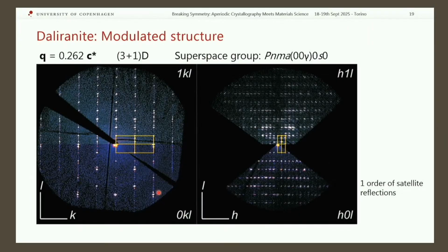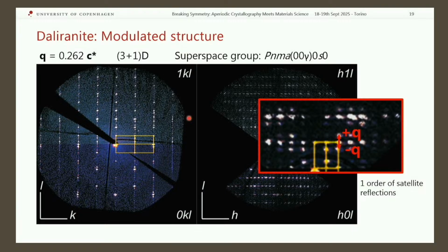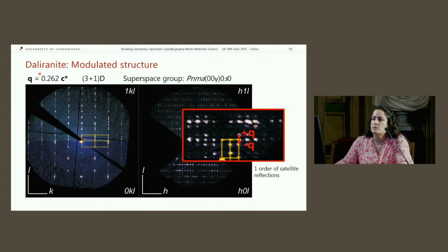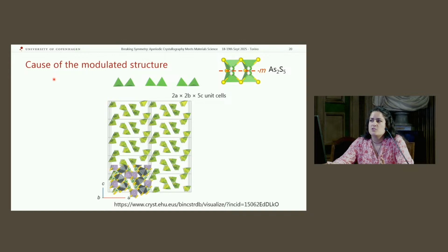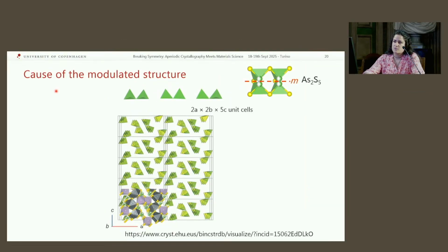But if we look at the reciprocal space, we see that our yellow unit cell here is not explaining all the peaks. So we have satellite peaks that are indicating there is some modulation going on, and we need an extra vector to index these peaks. So only one, fortunately. So this is a monodimensional modulation. We just need 3 + 1 dimensions. So you see the component here of our modulation vector is this strange number. It's not 1/3, it's not 1/4. It's, I think, like a 5/19. So it's an irrational number. This also tells us that the modulation is incommensurate. Good. From this, with the superspace approach, we can determine the incommensurately modulated model.